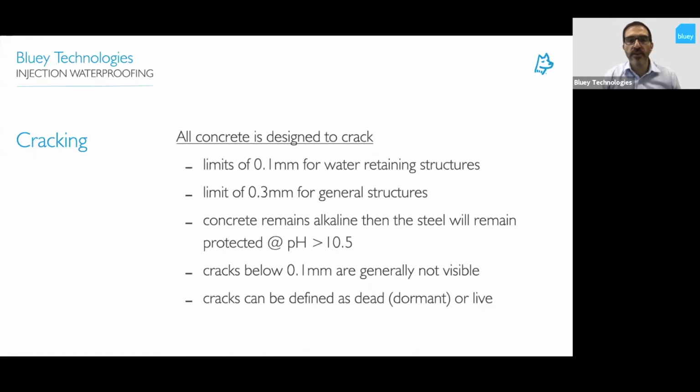I mean, that's the way you design it. It cracks and the steel takes the tensile loads. So we usually limit the crack width to 0.1 millimeter for water retaining structures, and typically there's a 0.3 millimeter limit for general structures. There are standards all around the world which will cover those limits for different circumstances and environments. The concrete will usually remain alkaline and protect the steel up to those crack widths.